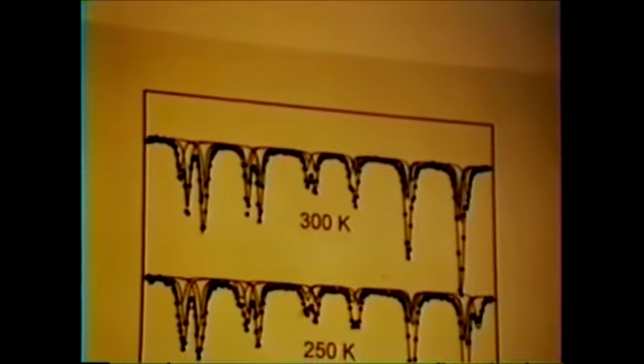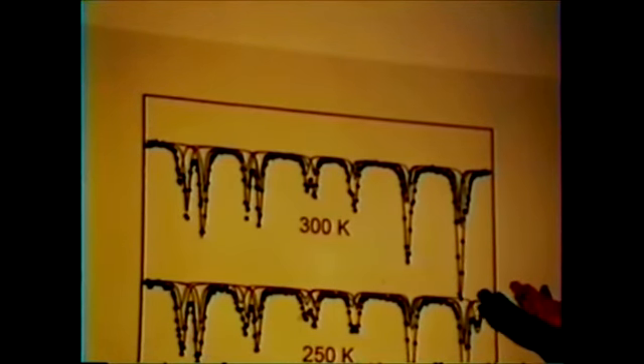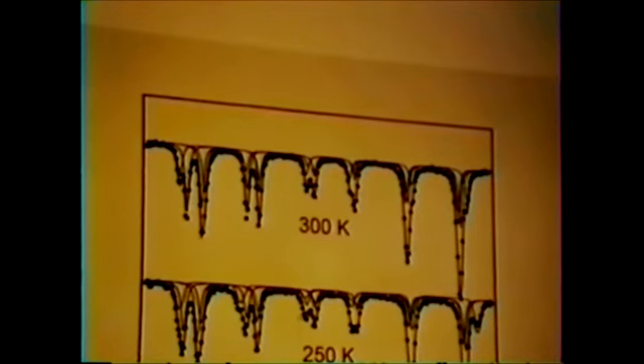Now, let me start with the magnetite. And actually, I will focus on the spectra taken at room temperature. This is non-stoichiometric magnetite, by the way, and I convinced Bob this morning that these two peaks, which they see as one peak, are such that one of them belongs to the B site. So for stoichiometric magnetite, you have this peak and that peak. One is ascribed to the A site, and the other is ascribed to the B site. And usually this is the formula for it, Fe3O4. You will have one iron 3 plus on the A site, and you will have iron 3 plus and iron 2 plus on the B site.